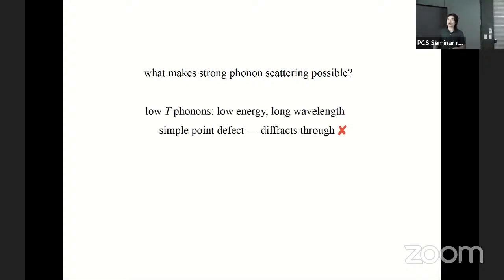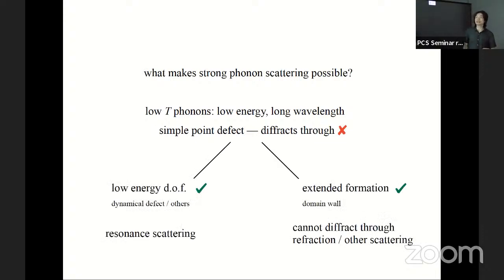In general, at low temperatures, phonons have very low energy and very long wavelength, right? Because they are gapless, low energy means long wavelength. So a simple point defect would not scatter phonons strongly, because something with long wavelengths would just diffract through a point defect. That means to strongly scatter phonons, we need one of two possibilities. One is maybe there's some low energy degree of freedom, such as a dynamical defect, so that it can couple with the low energy of the phonon and form some kind of resonance. The other possibility is we have some extended deformation, some large size thing, that can match the long wavelength of the phonon, such as a domain wall that we just saw in STO. So because the phonons are low energy and long wavelength, to scatter the phonon, we either need something of low energy or something with large size, okay?